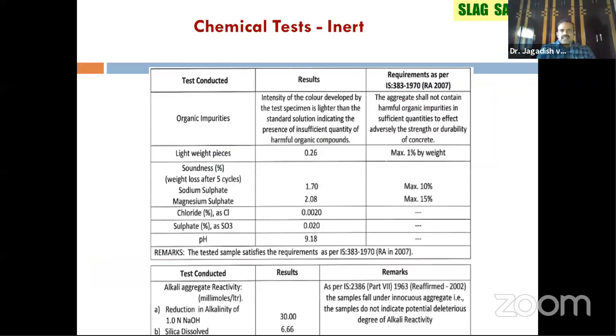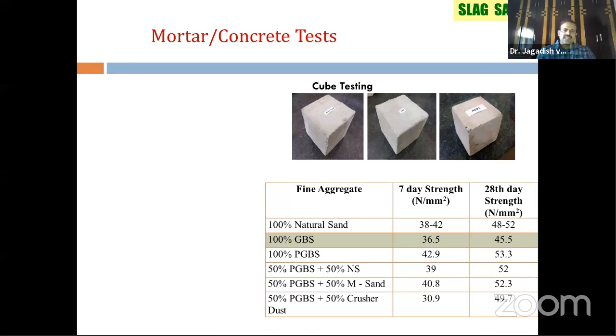So chemical tests were also conducted for this processed slag as per IS 383, as I mentioned. They conducted soundness tests, chlorides, sulfates, and pH. So when they check, it is much lower than the maximum requirements. Suppose take the case of magnesium sulfate, maximum 15% is allowed, but this is only 2%. And even alkali aggregate reactions.